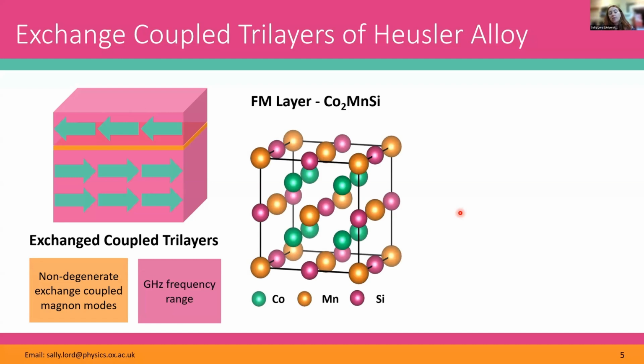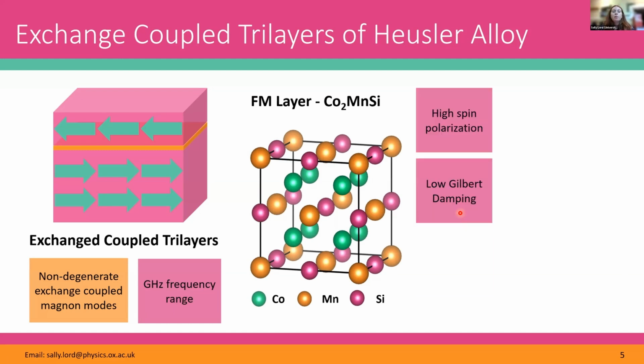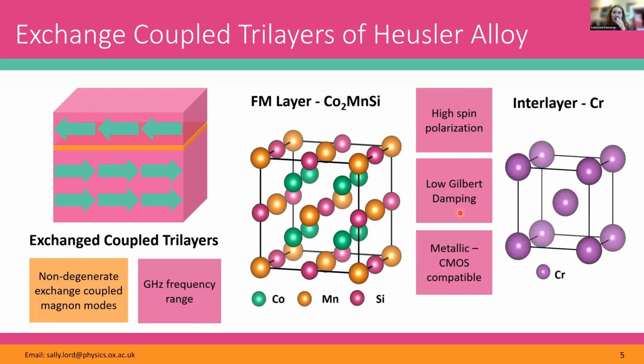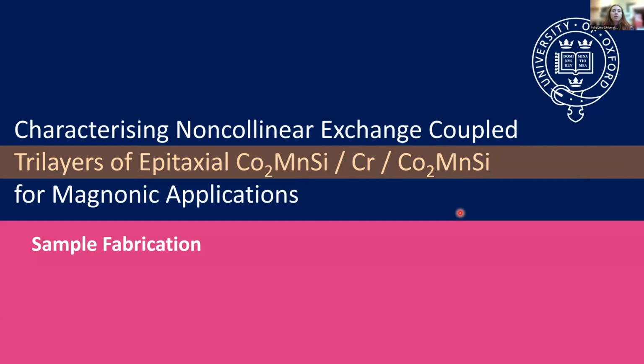And so one choice that could be good for Magnonic applications is this Heusler alloy cobalt manganese silicon, because it has a number of properties that would make it advantageous, such as the high spin polarization, the low Gilbert damping, and it's also metallic, which would mean that it's easier to integrate it with existing CMOS technologies. So in the following slides, I'm going to present our study on the exchange-coupled trilayers of cobalt manganese silicon with the chromium interlayer.